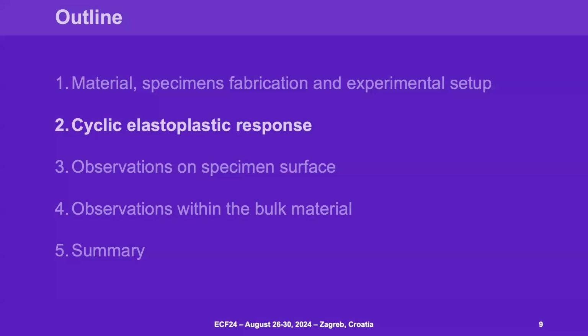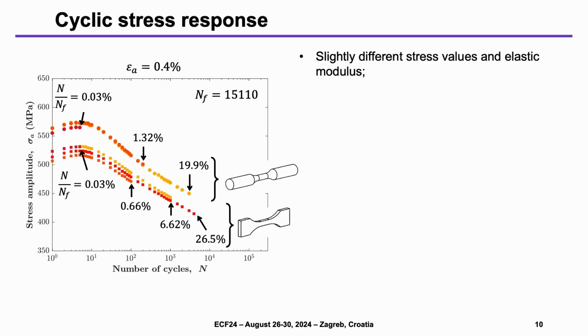Okay, so before I present the microstructural observations, I would like just to show the cyclic elastoplastic response during this low cycle fatigue test. As you can see here, both types of specimens exhibit cyclic hardening for the first 5 cycles and then cyclic softening, as expected.